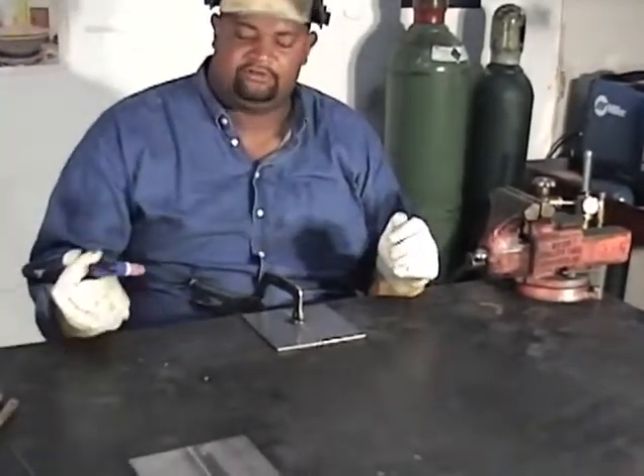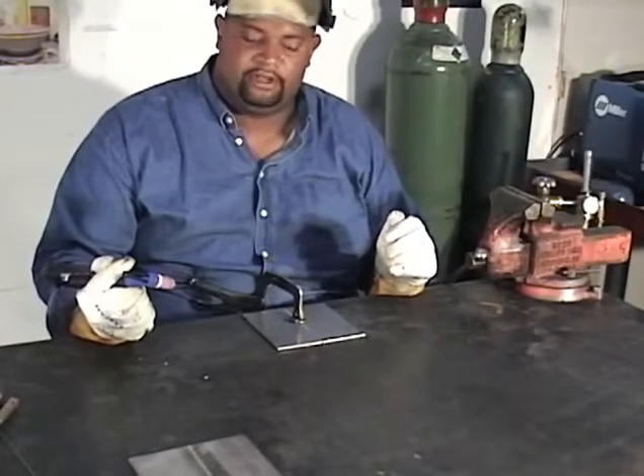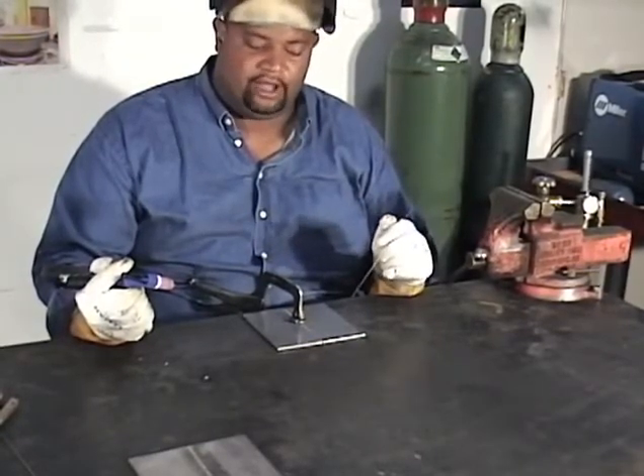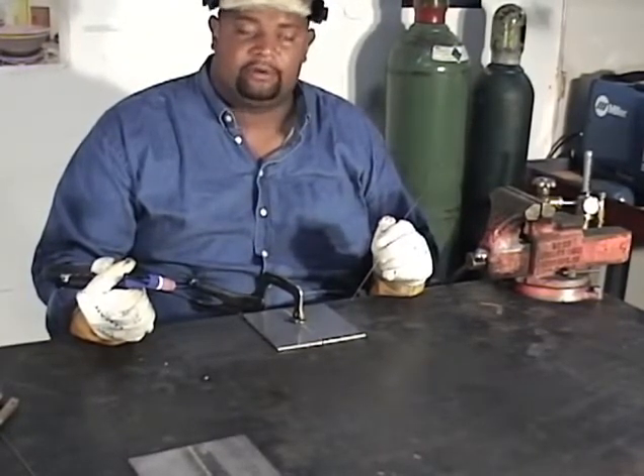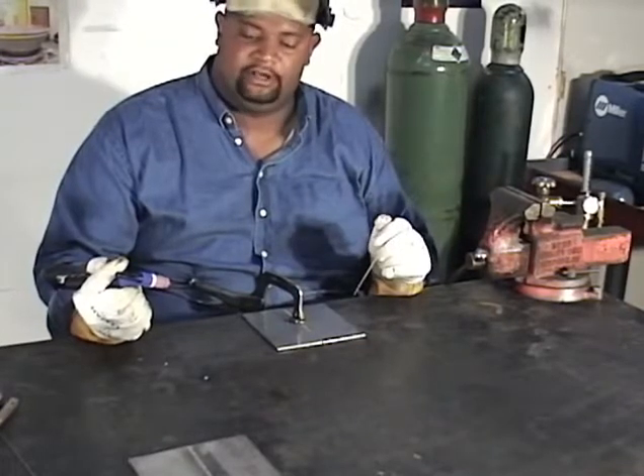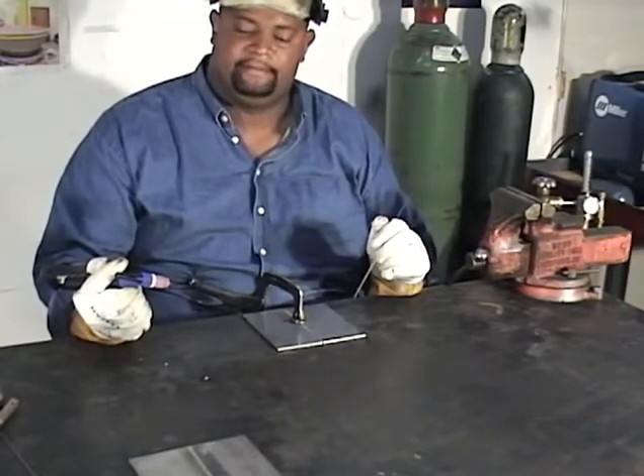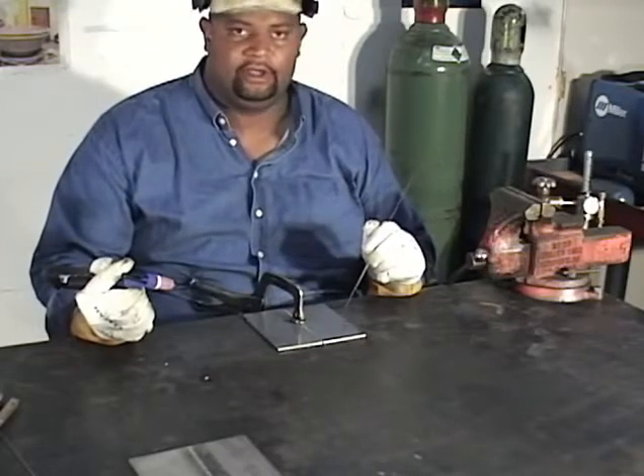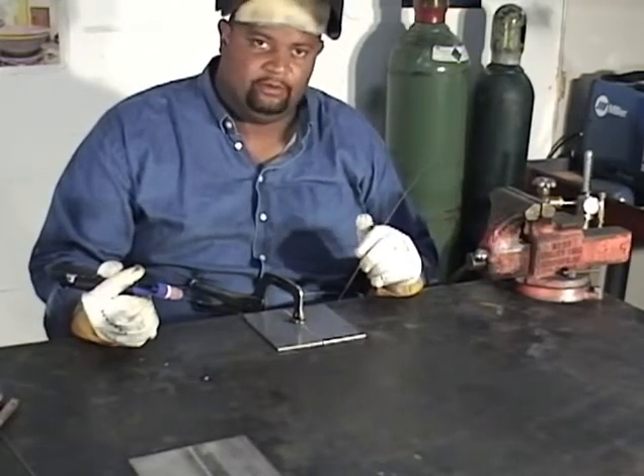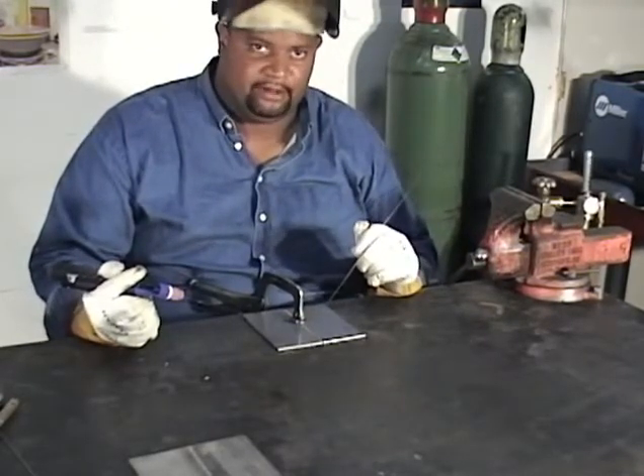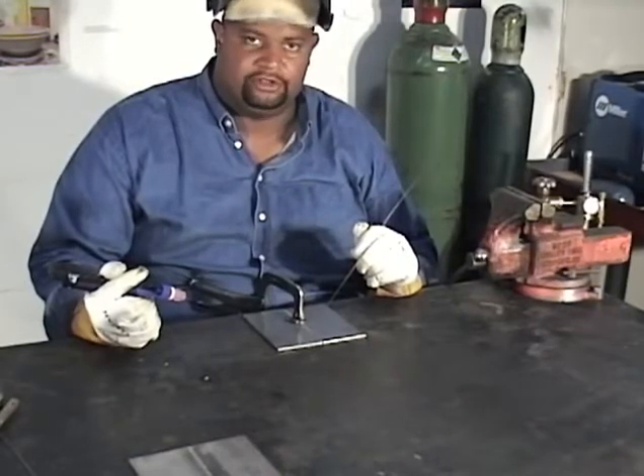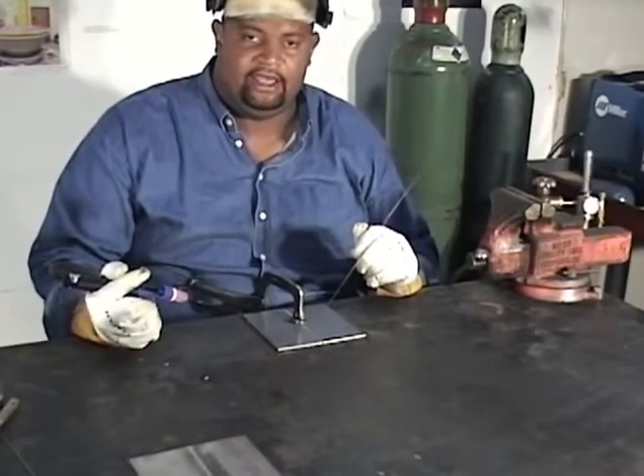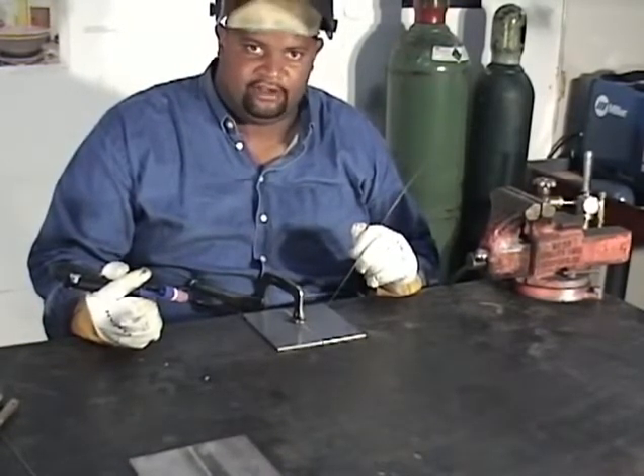You always want to get your gas flowing first before you tack, because if you tack the plate before having your gas flowing, you'll get porosity. So I'm going to hit the foot pedal. Gas is flowing, and for reference purposes, I have the weld machine set at roughly 100 amps. I'm not going to use the whole thing. I'm using about 75 to 80 of that, and the gas is flowing at 30 CFM.